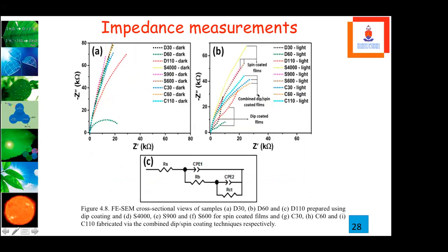Another experiment is that we have established in our lab electrochemical impedance spectroscopy, where we are able to do measurements for hematite in an aqueous solution. And we are able to produce very nice results, which you can see here for dark measurements and for the light measurements, using either combined coating or dip-coating methods.